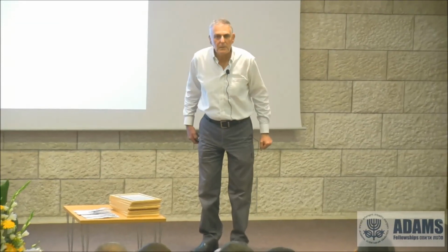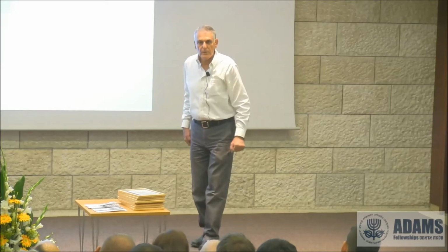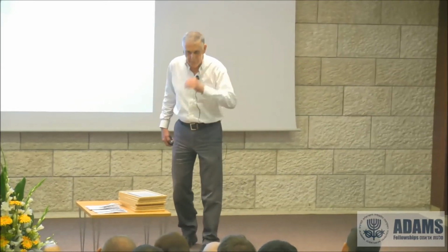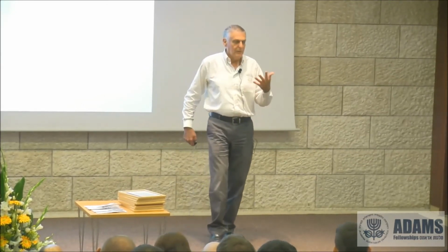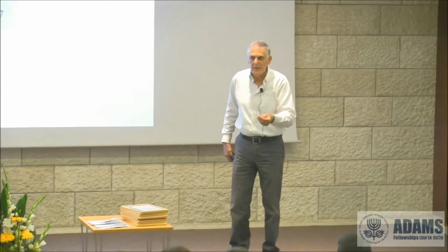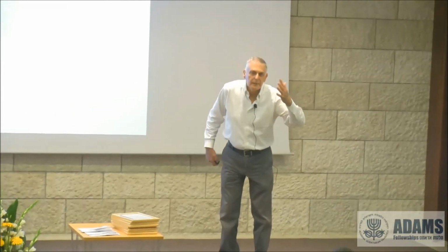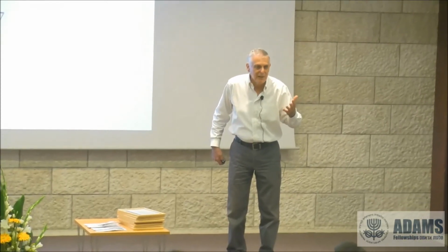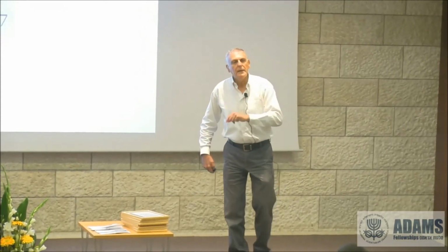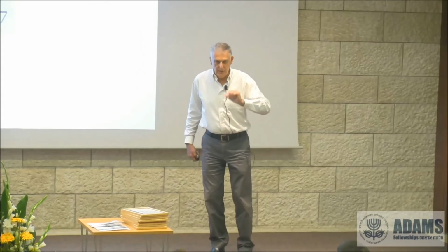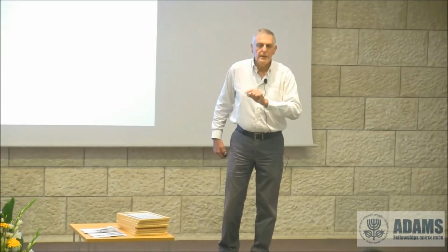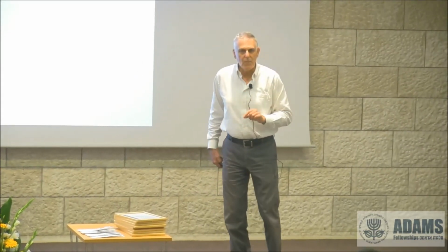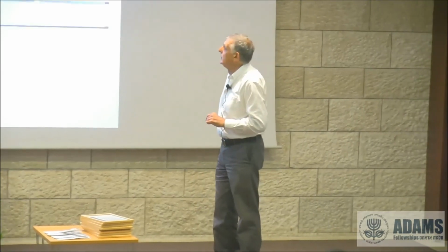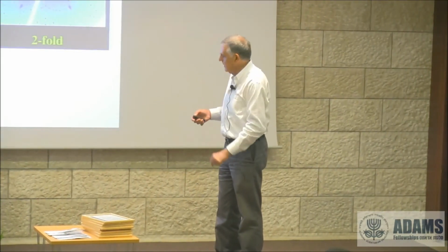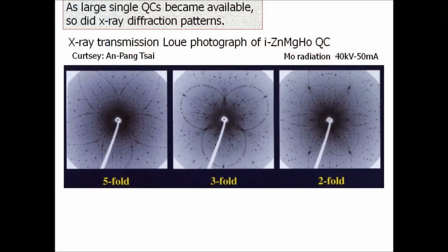We could not give them X-ray diffraction because our crystals were very small. Very, very small, 1 micron in size. And in order to have a diffraction pattern for one quasi-periodic crystal, you need a crystal to be about maybe 1/10 of a millimeter. That's good enough. We didn't have that. But in 1987, my colleagues in France and in Japan succeeded in growing large enough crystals for X-ray diffraction.